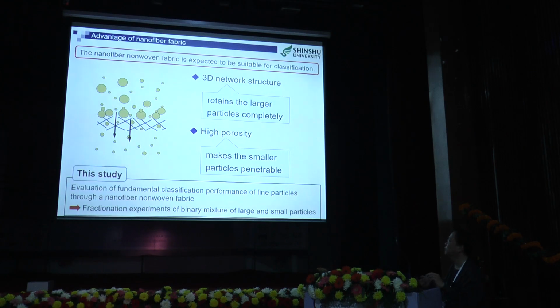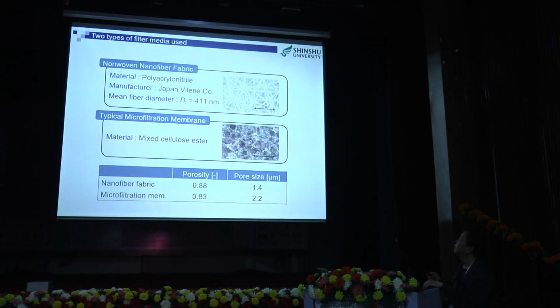So, in this study, in order to evaluate the fundamental classification performance of fine particles through a nanofiber non-woven fabric, we conducted the fractionation experiments of binary mixture of large particles and small particles. We use a non-woven nanofiber fabric made of polyacrylonitrile with mean fiber diameter about 400 nanometers. For reference, we use typical microfiltration membrane made of mixed cellulose ester. Their porosity and pore size are as follows.